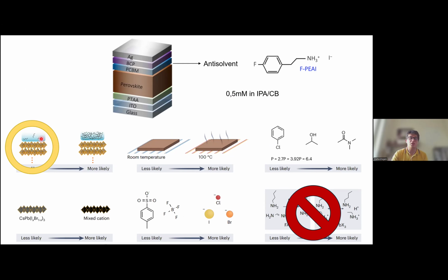So I'm using such a tiny and dilute solution that basically I'm most likely not gonna form a low-dimensional perovskite. Also, obviously, the other parameters play a role in the formation or not of this low-dimensional perovskite, but this one, since I'm using such a tiny amount, basically is dominating all the others.